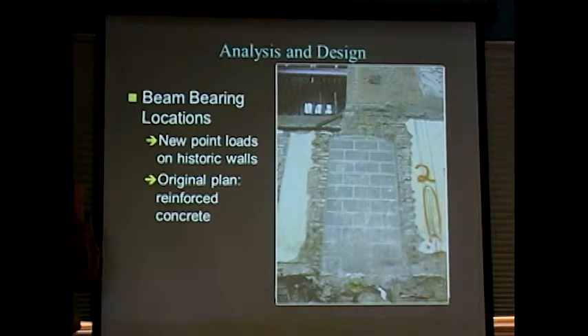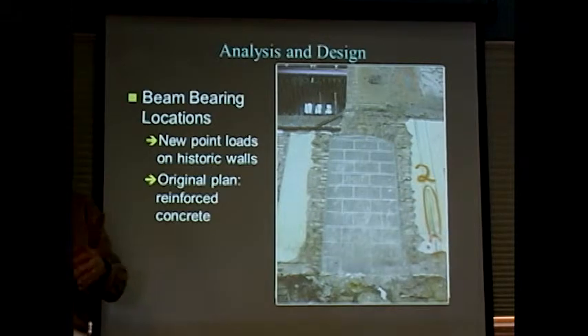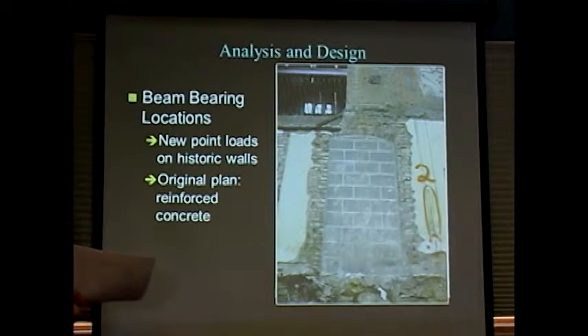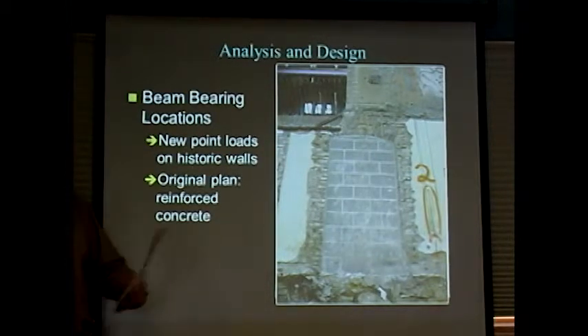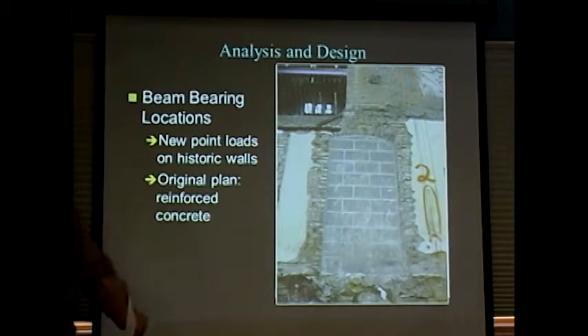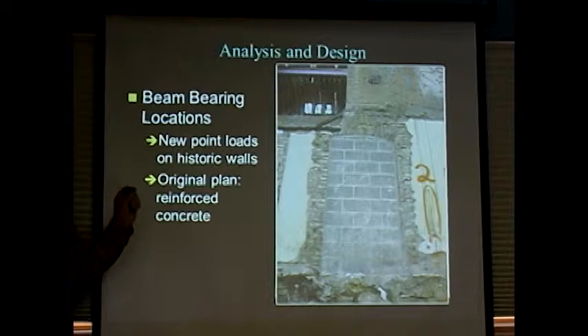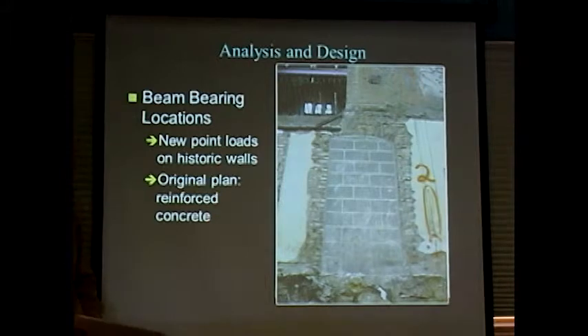And it sounds okay, but there's such a huge stiffness mismatch between modern concrete and historic brick. I'm convinced it would have cracked up like mad. And the face brick would have had cracks, the adjacent brick would have cracked up, and they gave us a hard time about that because our plan did not include reinforced concrete. I'm not so sure it was any more expensive than concrete, but they gave us a hard time about deviating from that concrete plan. But I felt vindicated because about 6 months after we were done with our work, they had infilled some door openings with concrete block, actually beneath some beam bearing points.